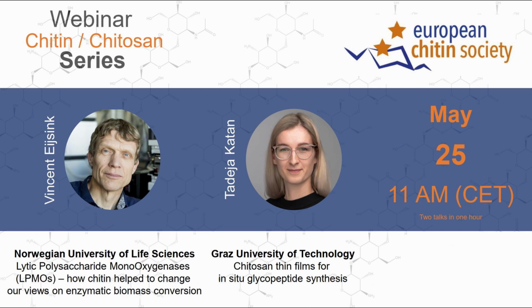At which pH did you perform this glycine coupling, the amide coupling, the carbodiimide coupling you mentioned? At which pH was that performed, and what implication does that have on the whole immobilization efficiency? We tried it with lower pH, and it did not work as well. So we then went on with a pH of about 9, and this is where the most successful results were obtained from.